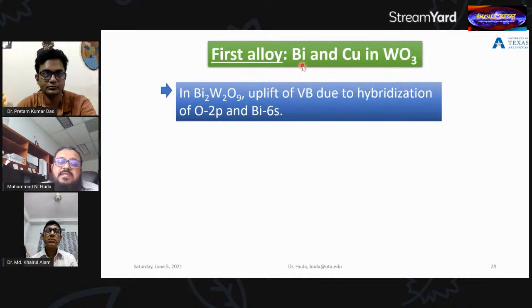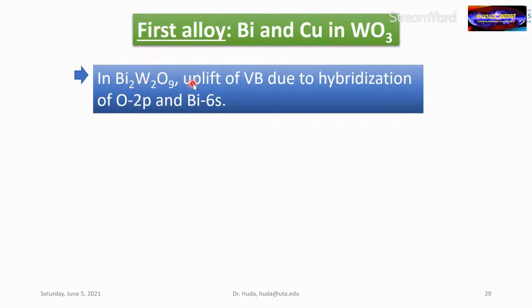Now, why did we choose bismuth in the first place? We found that in this compound, which is well published and included in crystalline databases, like one of the biggest, ICSD, a European database, and in the USA, the American Mineralogist database, and also from published papers, bismuth, when it goes into tungsten oxide, uplifts the valence band. It raises the valence band because of oxygen 2p and bismuth 6s hybridization or coupling. Bismuth 6s electrons are sometimes called lone pair electrons, but these are stereochemically active. Hence, this phenomenon happens. So if the valence band rises from tungsten oxide, the gap is now reducing.